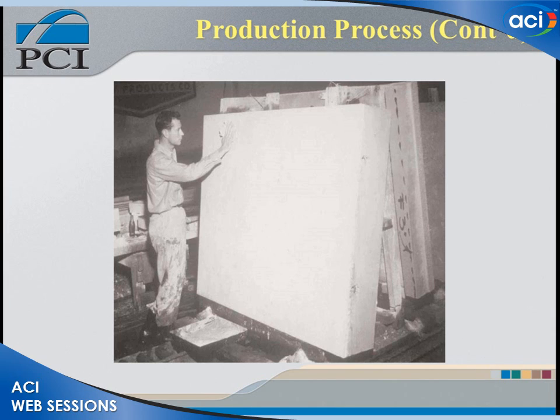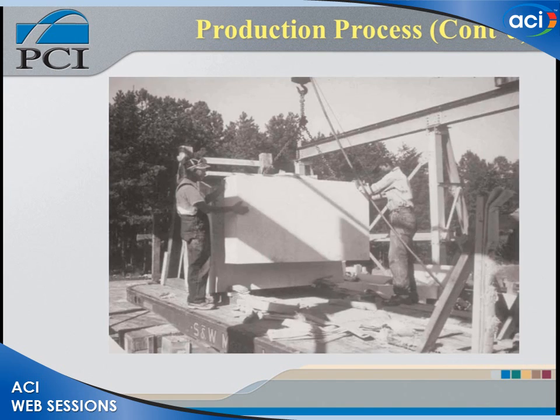The slabs then were subjected to further curing for 4 more days, wetting them twice daily. On the 7th day, they were given a final light acid etch wash of 1 part muriatic acid in 7 parts of water, except for spots that might need a stronger application to bring them to the desired texture. The panels were then ready for shipment. These slabs are shown being placed on a trailer truck. The slabs were stored both in the yard and on the truck on wooden easels.